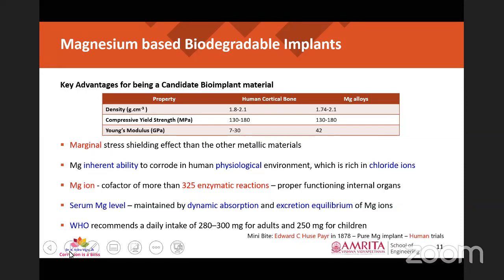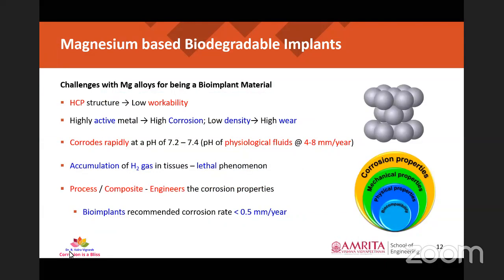The challenges of magnesium alloys with respect to bioimplant applications start with its HCP structure. The HCP structure limits the workability of the material. As we all know, the slip systems with HCP are very limited, so the workability is obviously limited with magnesium alloys. And added to that, it is a highly active metal that results in high corrosion rate, and the low density of the material will result in high wear rate too. Obviously, we know magnesium has a density of around 1.7 gram per cc.